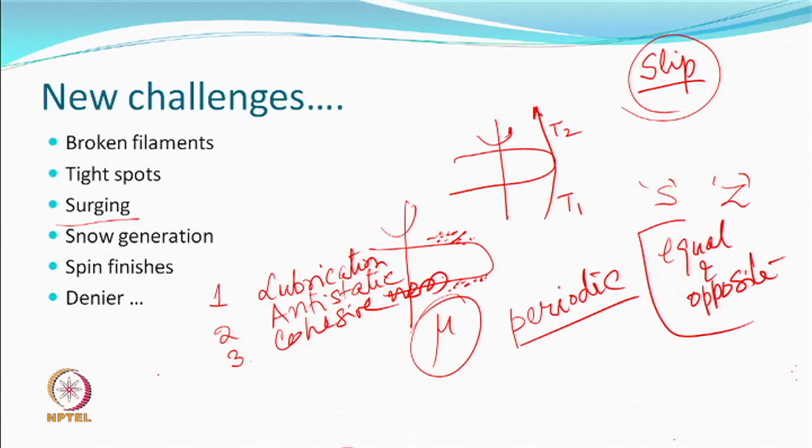The denier. So, denier normally should not be any difficult in finding out. In the earlier case, there was no issue anyway. The moment you do draw texturing, you start with a denier of a POY and end up with the denier of a textured yarn, and we hope that they will be correlated with the draw ratio. But because some of the properties may change because you change the draw ratio, or you are bound to change the draw ratio, the denier could be different. So, draw ratio can change, some of the mass can go as snow, the fiber may shrink also after or during this process of setting, and so you are just hoping that this will be the denier. You cannot really say, well, I can give you a mathematical arithmetic number, this is the denier. You may find it different.